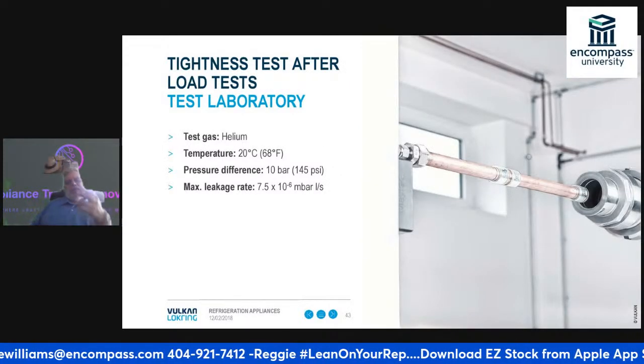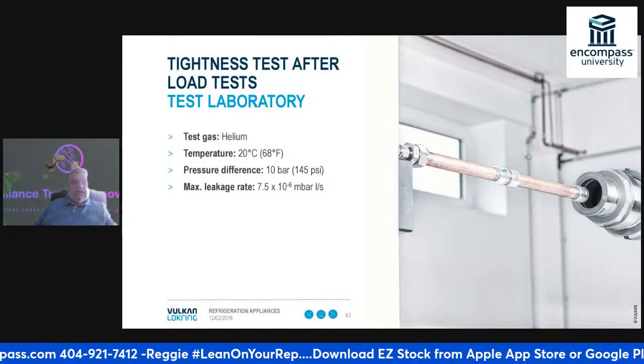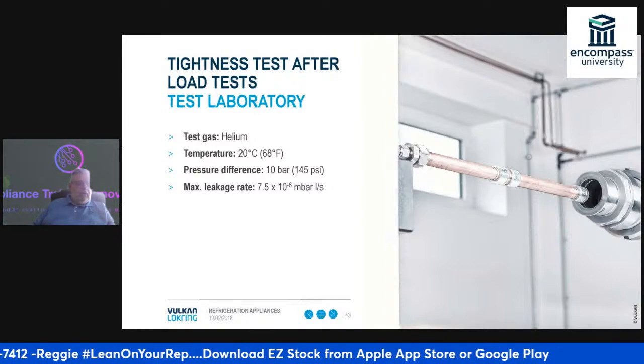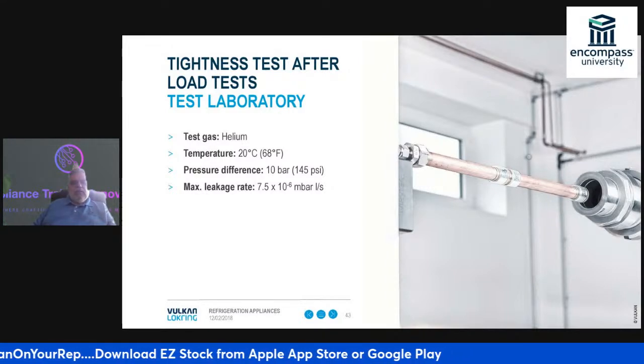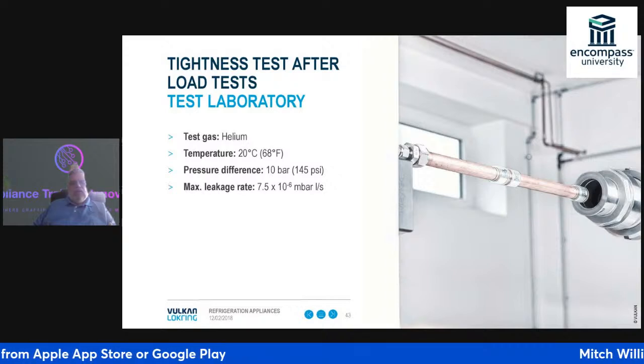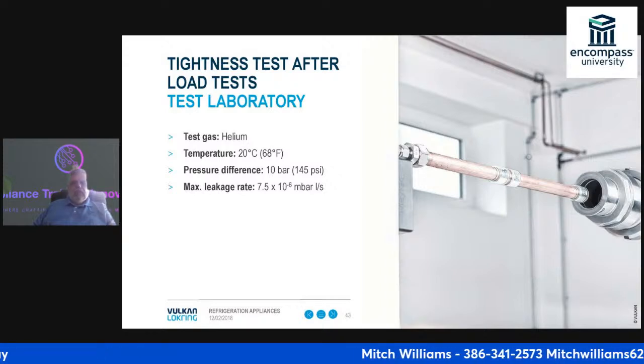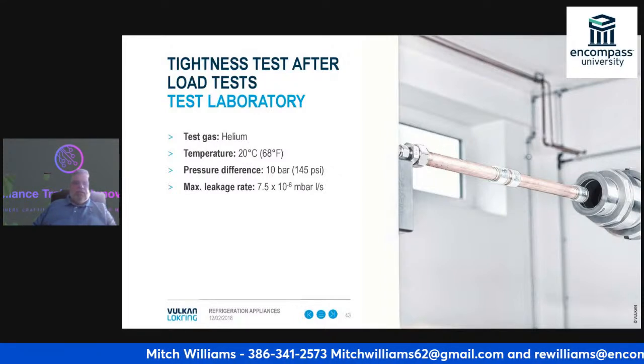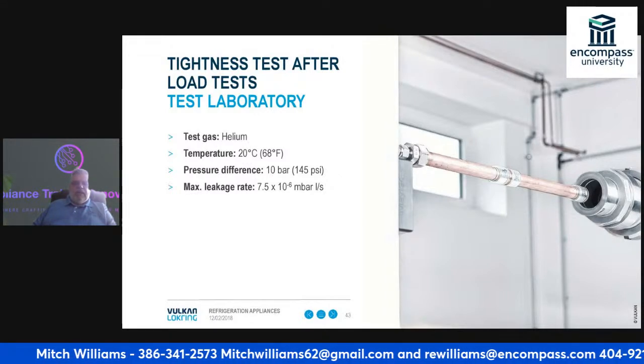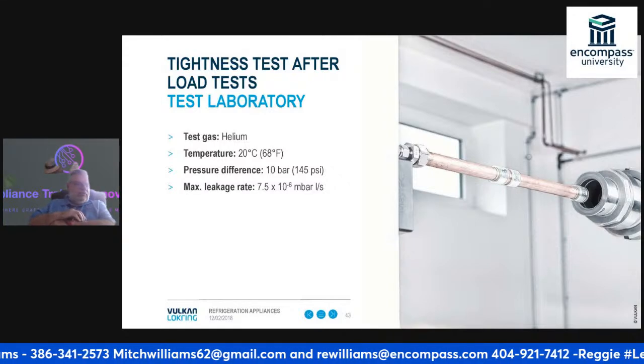Okay. Then at the very end, we go back to the tightness test. They're going to go back to the helium. We're at 68 degrees Fahrenheit, and we do 145 psi pressure difference. Okay, our maximum leaking rate is 7.5 times 10 to the negative 6 millibar.